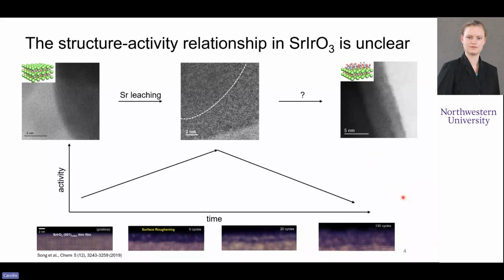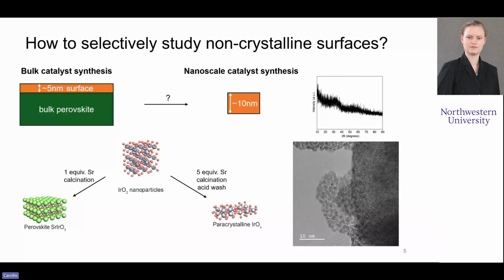How do we study an amorphous surface on top of a bulk crystal? Most characterization techniques out there are just going to give a signal from the bulk crystal, and it's going to be pretty much impossible to get anything from this really low crystallinity surface. And so our approach to that was to try and see if we can take this surface layer of the bulk perovskite, roughly 5 nanometers in depth, and we turn this bulk system into a nanoparticle system. If we make roughly 10 nanometer size nanoparticles out of it, one would expect those to exclusively be surface, basically. So they should be this amorphous-like structure without having a bulk crystal inside of them, and that should enable us to study them better.